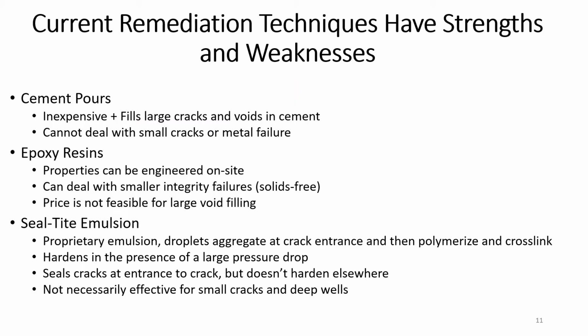Currently, there are a few methods for remediating failure at the wellbore. The first is cement pours, which are good for filling large voids in cement. It's cheap and bonds well with existing cement, but cannot be used if the failure cracks are small, or if it involves any of the metal casing. Epoxy resins can be engineered to work in a variety of environments and conditions and can fill some of the smaller cracks, as the resins can be made solids free, but their relatively high viscosities make it difficult for it to enter larger cracks.